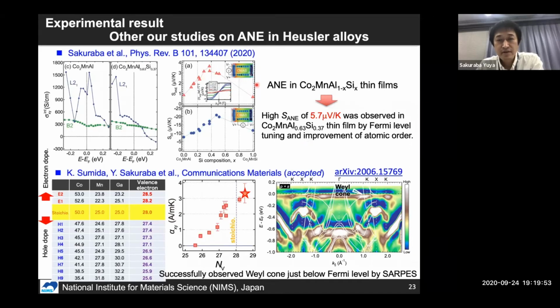So we also studied the anomalous Nernst effect in Co2MnAlSi thin film and observed a high anomalous Nernst effect of 5.7 microvolt per Kelvin. As with Co2MnGaGe, we confirmed the importance of Fermi level tuning and atomic order in this material. And we also fabricated Co2MnGa having different composition ratios, and you clearly see the large variation of alpha XY as a function of the total valence electron number.